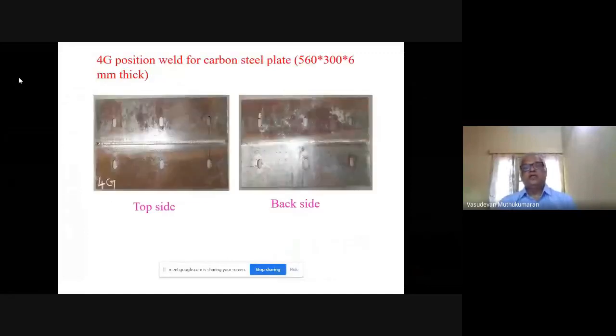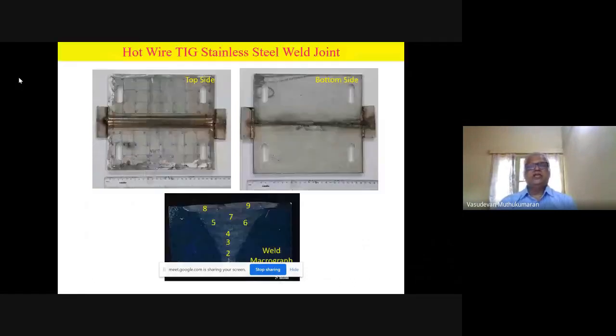All we could do successfully defect free, not only on carbon steel, we do on stainless steel. You can see here, this is again an 11 mm thick plate. You can see the top side, root side, and the cross section. It required some 9 passes to complete the joint. We could successfully pass radiography again.